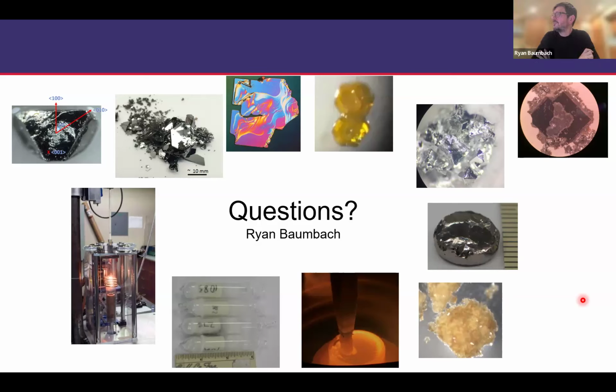I was just going to add that I don't know of a lot of works that go to very high pressures, although there was a series of experiments that I did when I was a graduate student when we were using a cadmium arsenic flux. And this was a nightmare because the pressure above the flux gets large. So we had to actually build a system. This was more a matter of strategy than influencing the crystal growth, but we would seal the material in a quartz tube. We would have a partial pressure in there that would counterbalance the cadmium arsenic vapor pressure. And then outside of the quartz tube, we had another steel tube that we loaded with partial pressure so that it would counterbalance the pressure that built up inside of the quartz tube. So certainly it can come into play when you think about strategy of how you will do something.